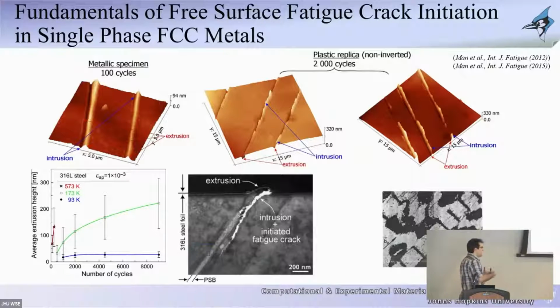These dislocations are the defects that lead to atomic slip in the materials. The black regions represent very high dislocation density regions. The white regions represent low dislocation density regions. So the dislocations, these defects that are in the material, start aligning into this specific structure. That structure becomes where localized slip happens. So the material slip creates that extrusion, and eventually that extrusion will be associated with stress concentrations, and these defects eventually lead to the formation of other types of defects, basically vacancies and interstitials. These vacancies contribute to the formation of cracks. Those are at least the theories that exist in the literature.